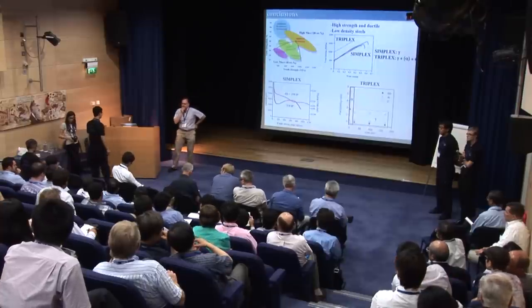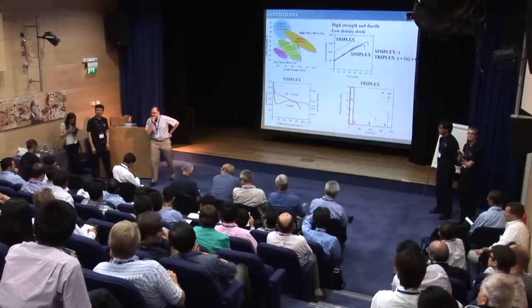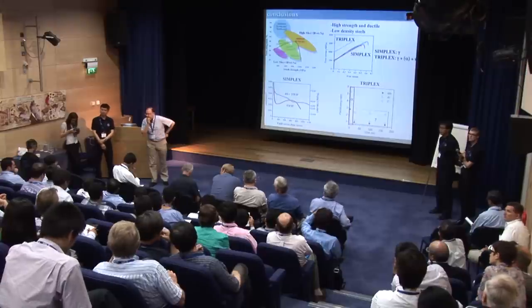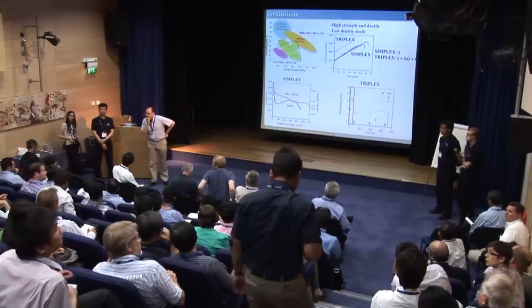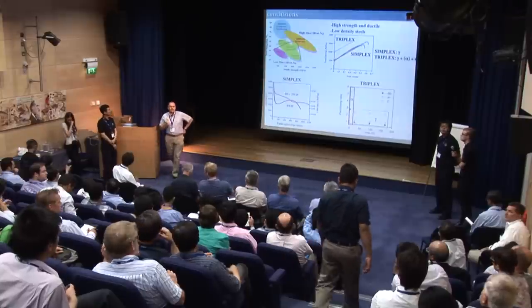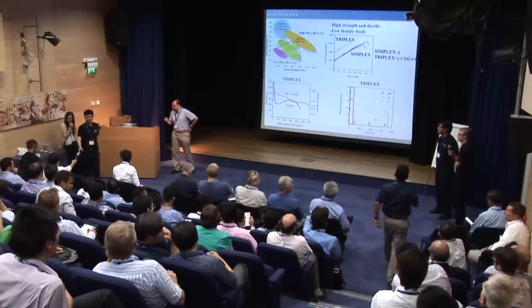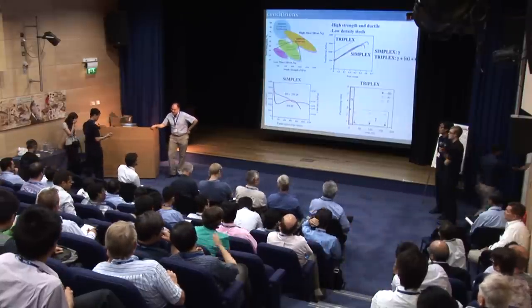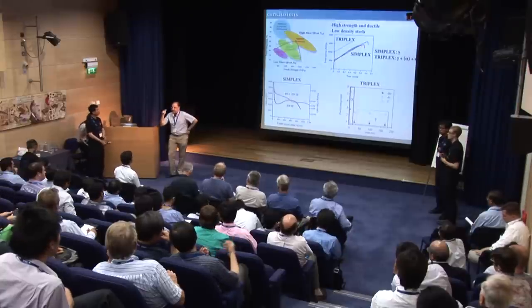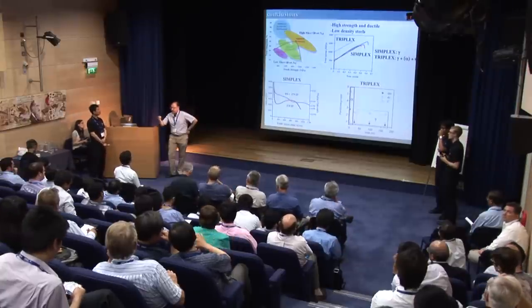How to control the kappa carbide in order to improve the elongation in the triplex steel? So this is a good question, because the formation of kappa in terms of annealing time is promoting ferrite at grain boundaries. This is what we have seen, not in this alloy, but with other alloys. If you add more aluminum, for instance, since the beginning, you probably have smaller particles, but ferrite is forming at grain boundaries. So in terms of damage mechanism of tensile ductility, it is even worse.